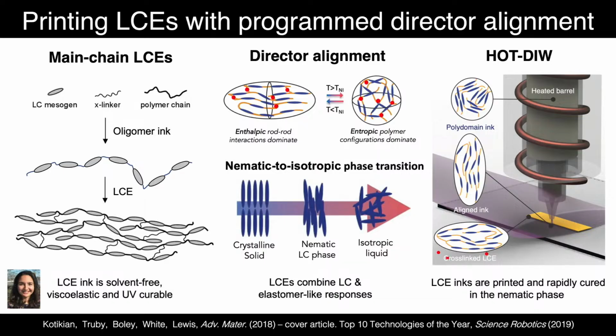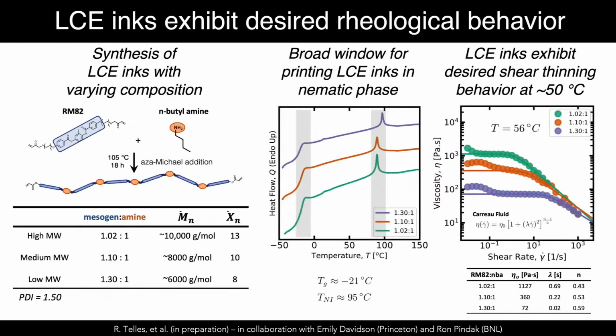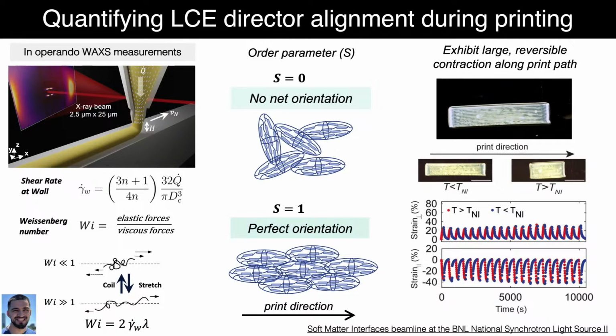So this material that we're depositing is in the nematic state, but at slightly elevated temperatures because these are pretty highly viscous. At this temperature, you can see that depending on the composition, we have different viscosity values, but they all fit very nicely to this value. Depending on the composition, we also have a pretty large range of relaxation times. So if we print correctly, we can in fact shear-induce alignment. And as I'll talk about in a minute, we can assess the orientation parameter, the order parameter.